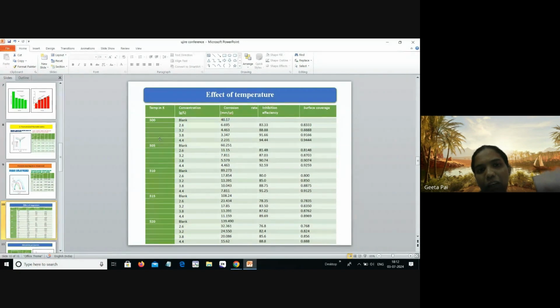From the result, it can be confirmed that from 300 to 320 Kelvin, the corrosion rate value increases, whereas the inhibition value goes on decreasing. This indicates that as the temperature increases, the corrosion rate value increases, but the inhibition value decreases. Therefore, for 300 Kelvin at 4.4 ml, we get 94% inhibition efficiency, but for 320 Kelvin, for 4.4 ml, we got 88% inhibition efficiency. Therefore, at a higher temperature, the inhibitor is unable to withstand on the metal surface.